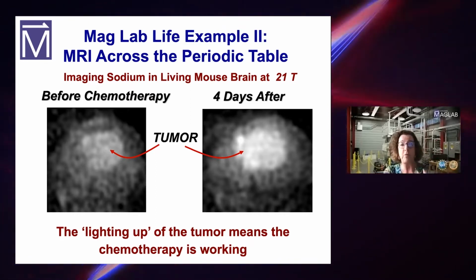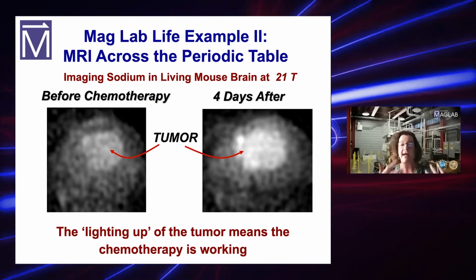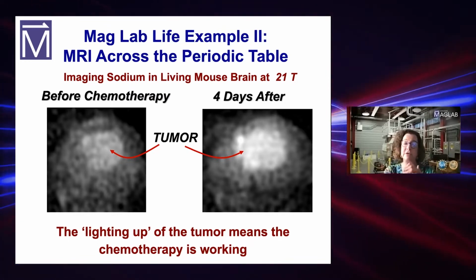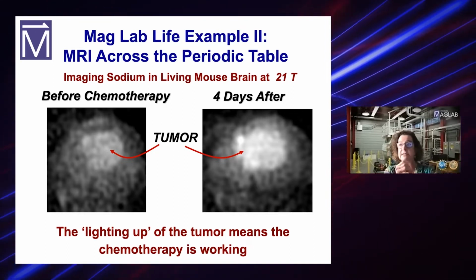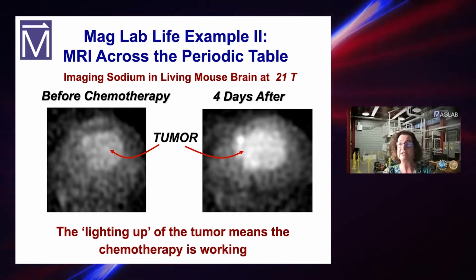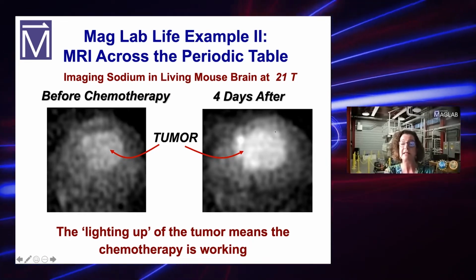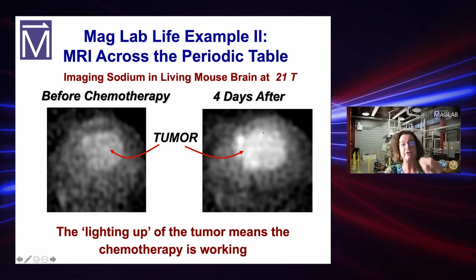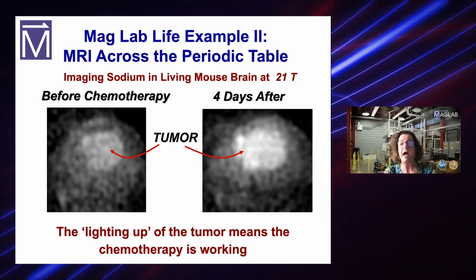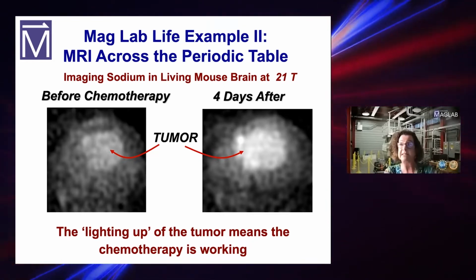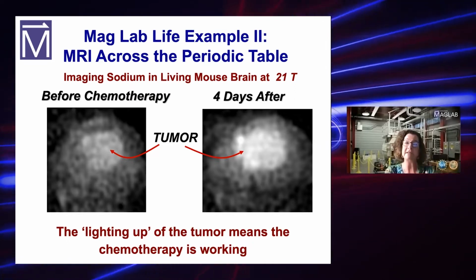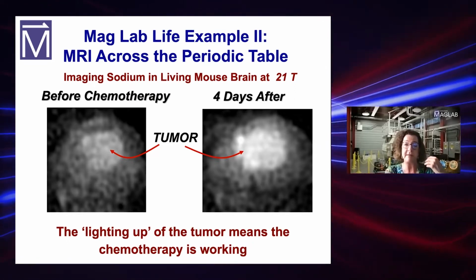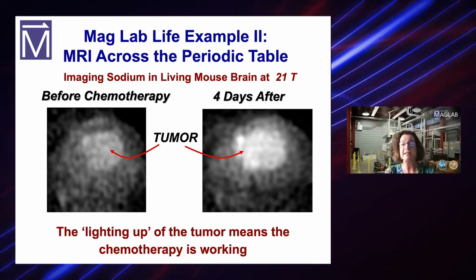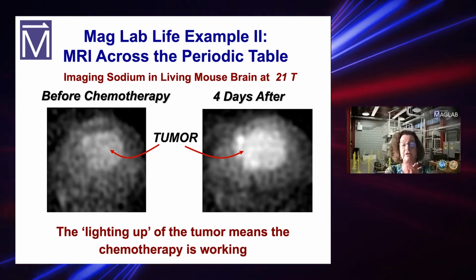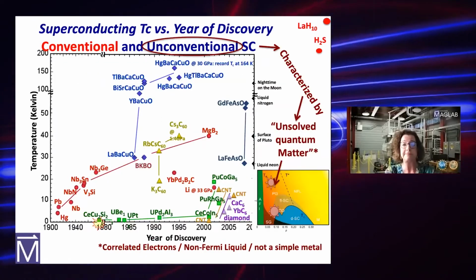We're not really sure why. We have some idea, but it doesn't matter. We just know this. So what you do is you give the rat chemotherapy, wait 4 days, and image again. You may have to do this several times, but if all of a sudden the sodium lights up, that tells you that the cells in the tumor are uptaking sodium, so are probably dying, and that gives you confidence that that regime of chemotherapy might be working. It's in the prototype stage, and it's only at the size to do rats, but it's a very promising technique.